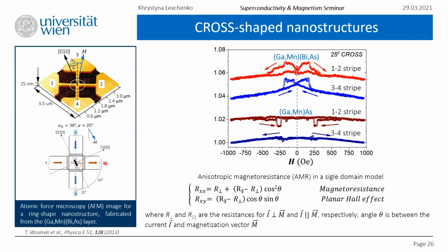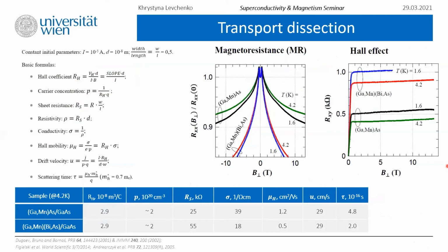So the principle of this functionality was checked by introducing different designs. A very important conclusion from this is that for the first time, nanostructures were fabricated from the gallium manganese bismuth arsenide layers. They show the non-monotonic magnetoresistive dependence on the in-plane magnetic field, similar to those of gallium manganese arsenide, but with an enhanced response that would be advantageous for magnetic memory applications.